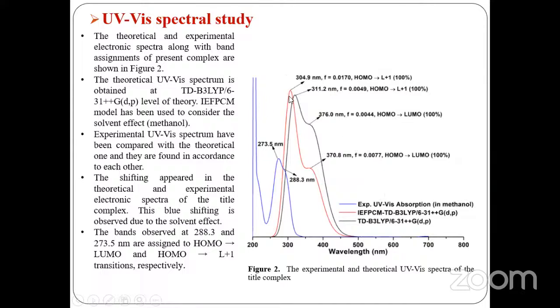And this is the UV-visible spectra of the complex. The blue one is the experimental UV-visible spectrum, and these are the theoretical UV-visible spectra. The red one is computed in the solvent phase, and the black one in the gaseous phase. The experimental spectrum has been compared with the theoretical one, and they are in accordance. Some shifting is found, which is due to the solvent effect. The bands at 288.3 nanometer and 273.5 nanometer are assigned to the HOMO to LUMO and HOMO to LUMO plus 1 transitions respectively.